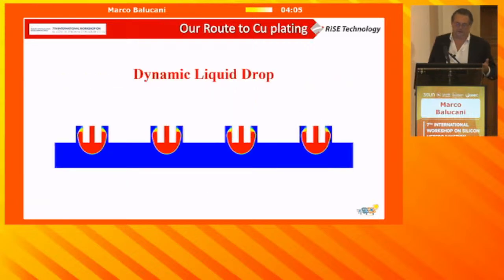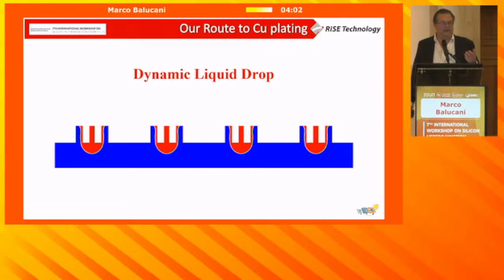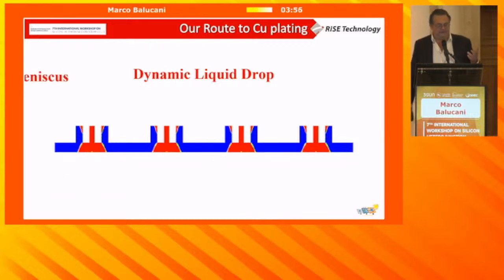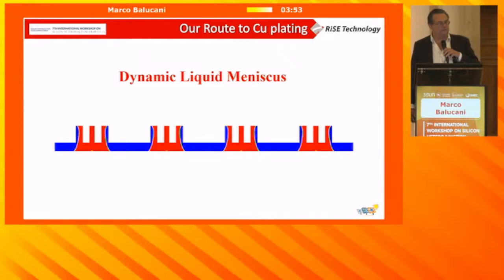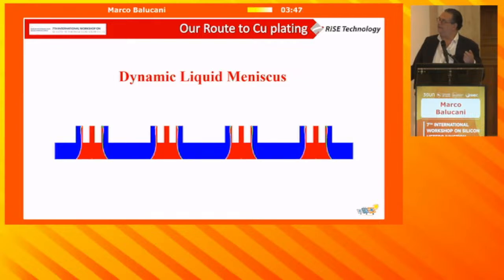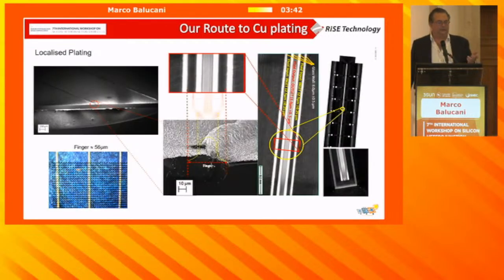So we do what is called a dynamic liquid drop. We confine the liquid, and this is the liquid that's changing, as soon as a surface arrives, we form what we call a dynamic liquid meniscus, okay? And each one of these is independent, so imagine, independently this liquid is like a damper, so it will adapt if you have non-uniformities and so on, okay? So here is how we make it. This is our nozzle, and here you see the plating. This is the liquid coming out, the speed of the liquid, and here you see, because we touch the solar cell only at this point, each dot is 50 micron, and the pitch is 100 micron between them.